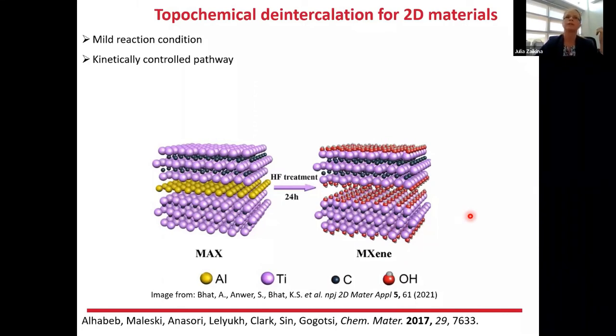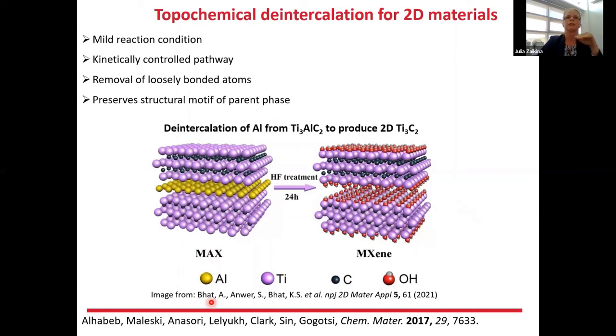So this method provides very mild reaction conditions. It's typically done at room temperature, and it's a kinetically controlled pathway. So for instance, if we start here with titanium aluminum carbide, which has this layered structure, we can remove the layer of aluminum by treating this material with HF. In our case, instead of aluminum, we have lithium, which presumably should be even easier to remove.